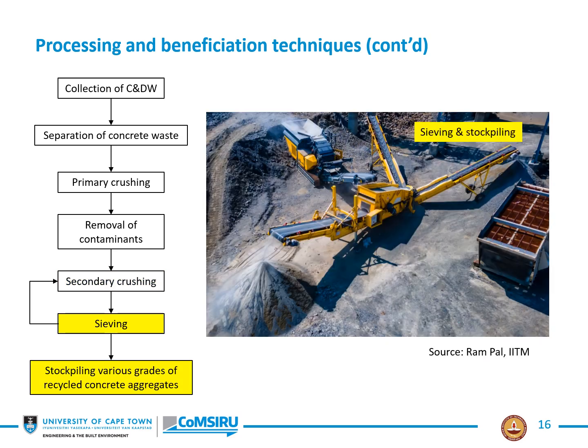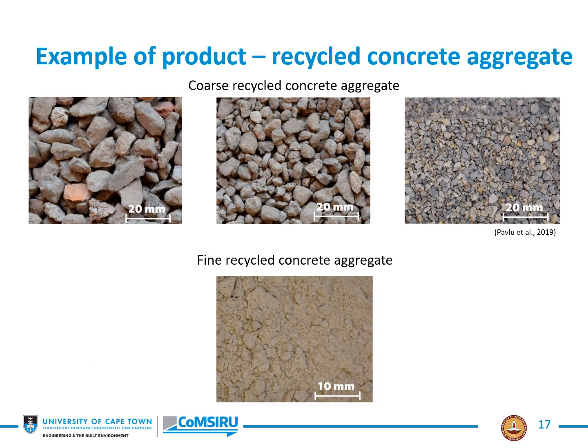And then into sieving. So here is a mobile crusher. Here is a mobile sieving machine, where from the crusher, the stream is then separated into, in this case, coarse aggregate over there, or recycled aggregate, and the fine material landing up over there. So we land up with stockpiles of various grades of recycled concrete aggregates. Example of what I mean. Here are 3 examples of coarse recycled concrete aggregate as a function of particle size. And here's the fine recycled concrete aggregate that also comes from the process.